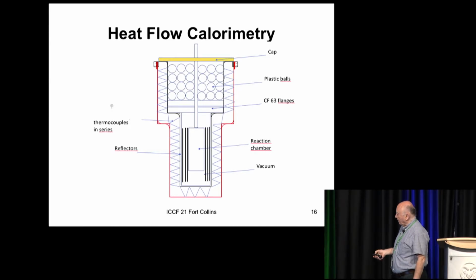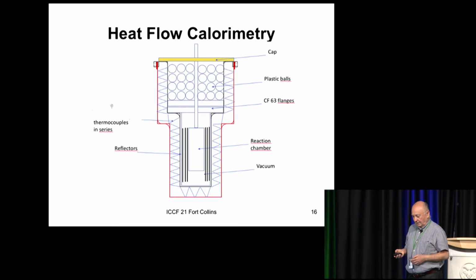You have vacuum around, then you have a layer of aluminum case, a double wall. In between you have an insulating layer, I will show you. And then I put 50 thermocouples in series, but only in one direction. Because of the cylindrical symmetry, you don't need so many thermocouples. You get the same signal, it's just amplified. So instead of volts, you have millivolts, but the result is about the same.